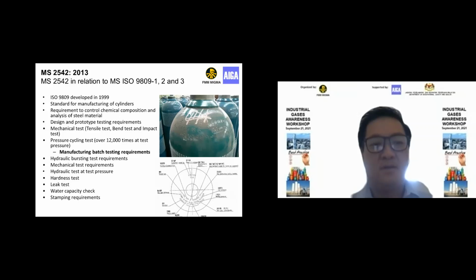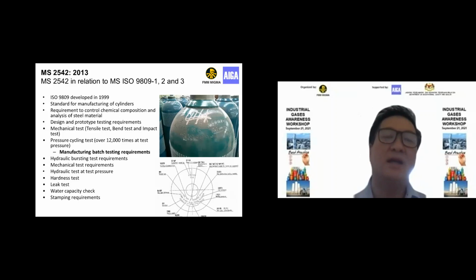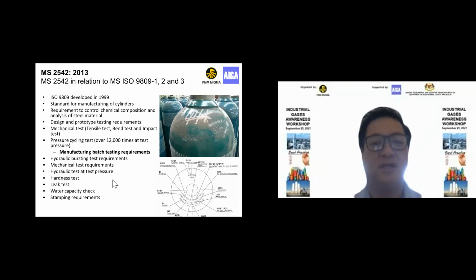Pressure test cycles for the batch testing requirements are up to 12,000 cycles. This would normally cover the entire lifespan of the cylinder. We are experiencing cylinders right now that last for 60, 70 years. So 12,000 cycles normally covers that entire period. Bear in mind the testing requirements need to be maintained as well while the cylinder is in operation. There are hydraulic burst test requirements, mechanical hardness tests. After that, there is a leak test, water capacity check, and also the stamping requirements. We'll talk about stamping requirements in the next few slides.